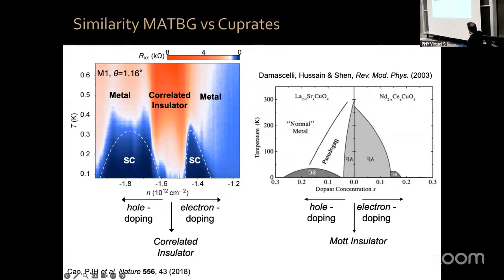So zero means 1 electron per copper atom; that is a Mott insulator. If you dope with holes, you get superconductivity. If you dope with electrons, you also get superconductivity. Here at this doping of 2 electrons or 2 holes in our system, we have an extra factor of 2 because of that valley degeneracy thing, remember?